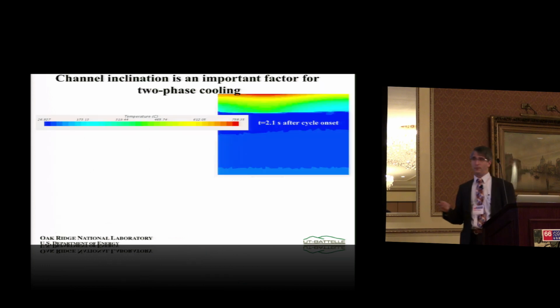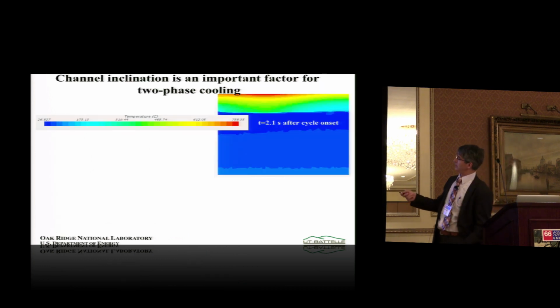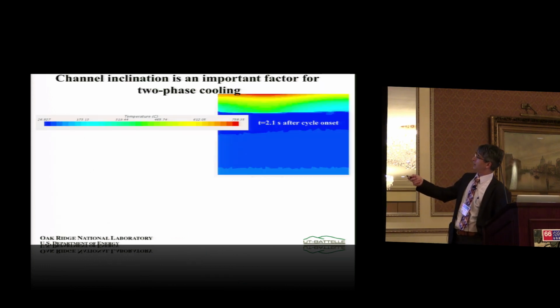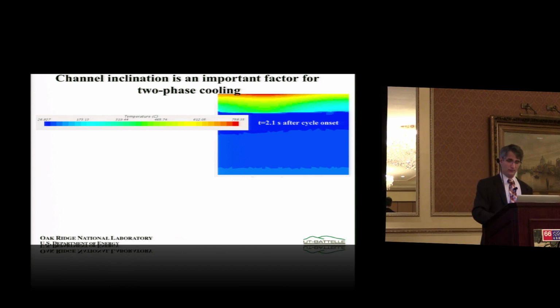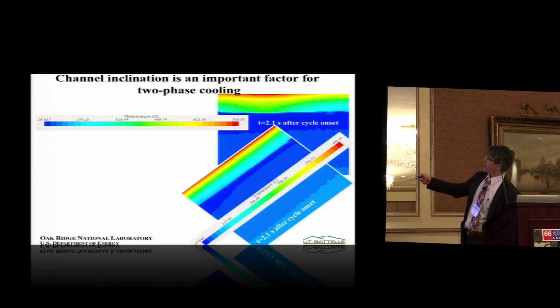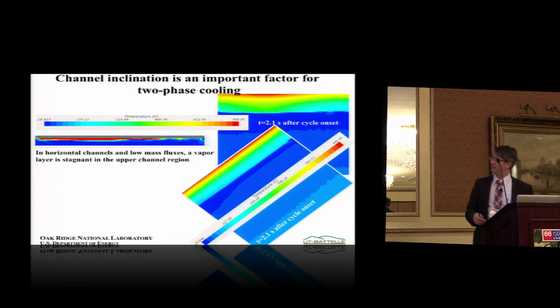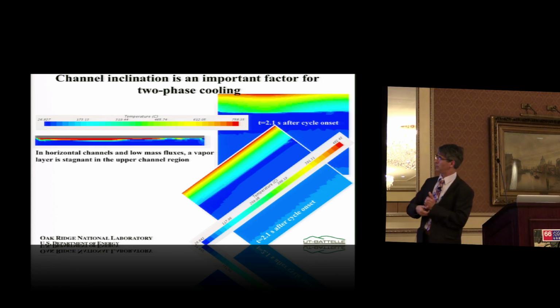So we got one example in which we actually found that for this configuration, the die overheats, exceeds far away our threshold of 600 degrees Celsius. And if we incline that channel, for the same flow rate, nothing else was varied, you get reasonable temperatures. So the inclination definitely has to be taken into account.